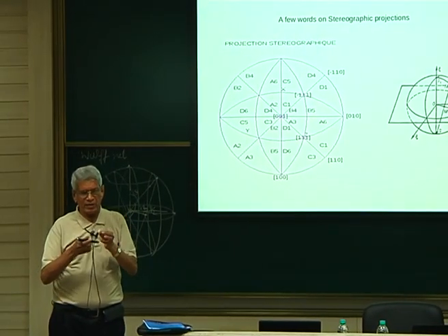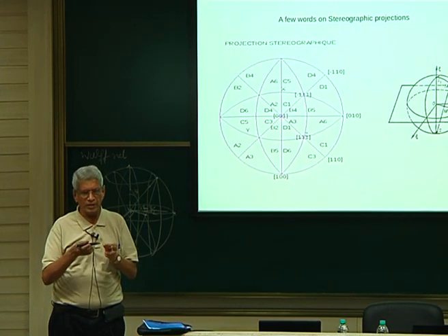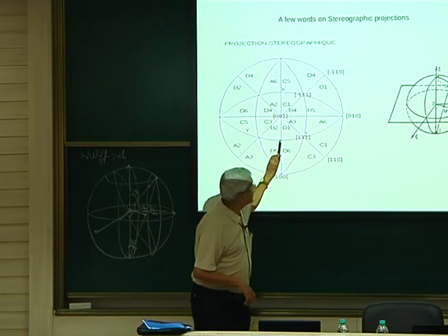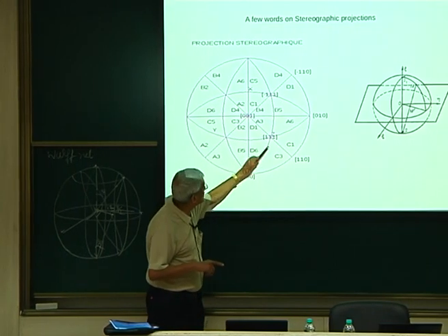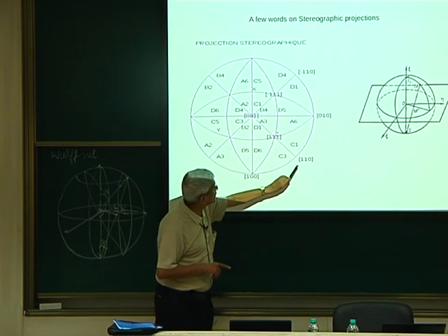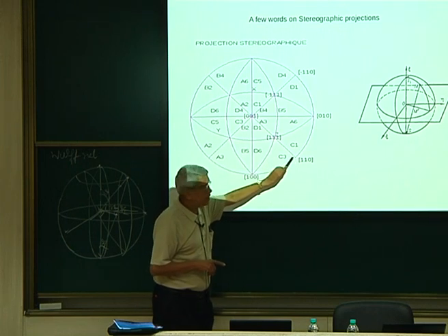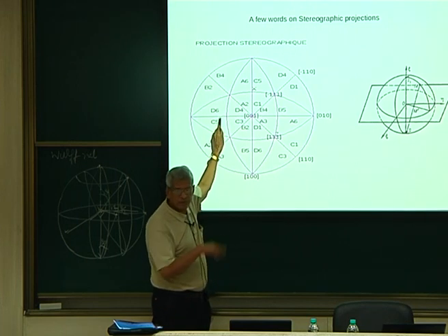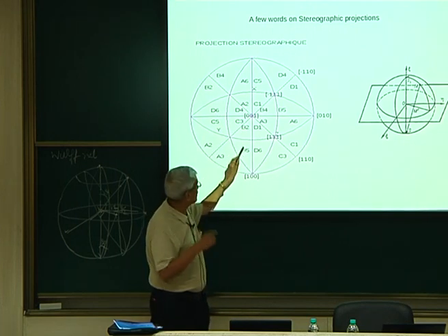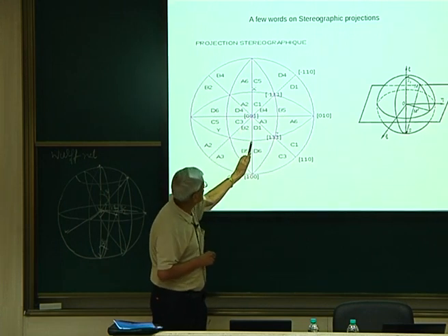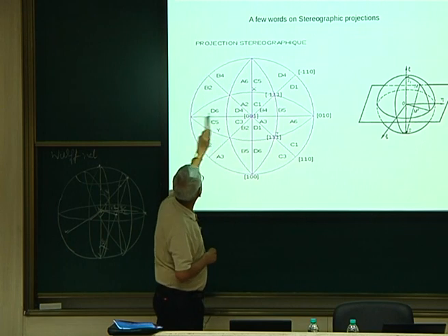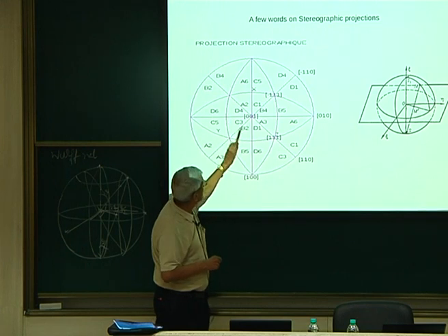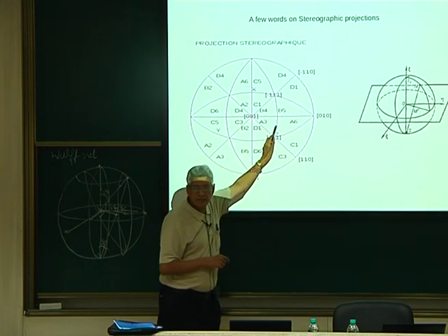So we know that a Burgers vector is going to lie in the slip plane. So with respect to a plane normal, it makes an angle of 90 degree, correct? That is essentially what we have done. And in FCC system, if you consider the 1 bar 1 plane, it's going to be either 110 or 101, and this will be 01 bar 1. When we index it, by vector addition, this and this if we add together will be 101. Here and here it will turn out to be 01 bar 1. So with respect to 101, if we see these two,